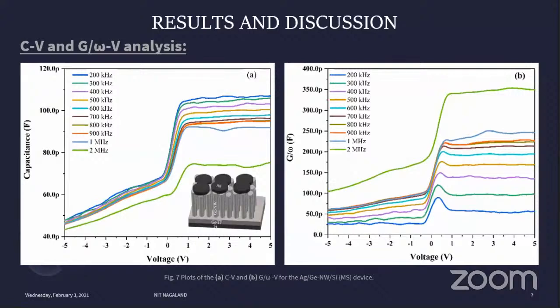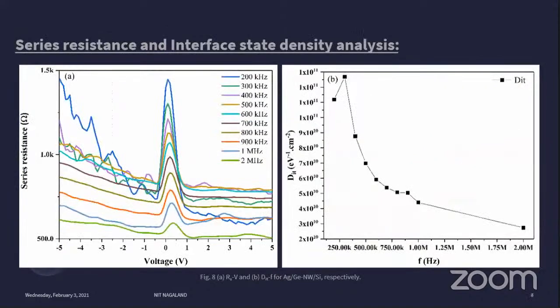In order to further understand the role played by the series resistance and the interface state densities, we have calculated the series resistance and DIT using the Nicollian-Brews method and the Hill-Coleman method. According to the series resistance plot, as we increase our frequency, the resistance value decreases, whereas DIT, the surface and interface state density, also decreases as we increase our frequency.